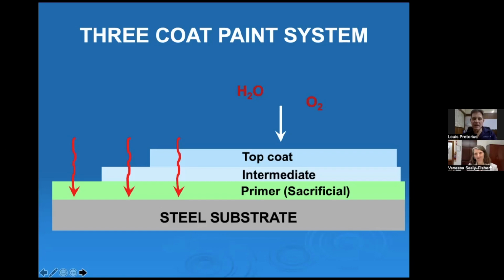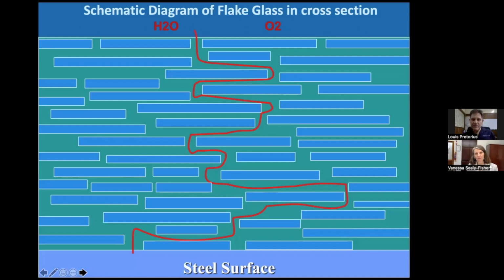So you could immediately see there that if you had a 5-coat system where you added 2 extra layers to that, you increased the total thickness, and you would then also take a longer time for the oxygen and water vapor molecules to get down to the surface. When we add flakes to a polymer or to a coating system, the flakes need to orientate similar to how they're on that schematic, so that we create a long path length.